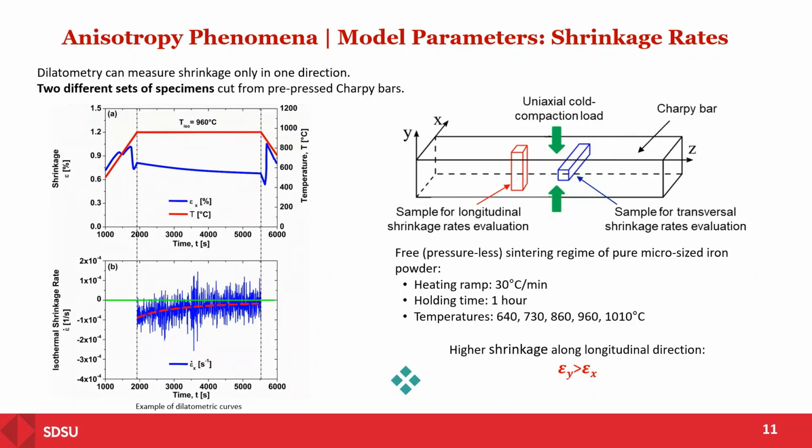So this shrinkage takes place while you still have that uniaxial pressure being applied. Right. Yeah, so in this work I also analyzed with dilatometry the same type of components, these Charpy bars, that were produced with different pressures, from, I don't know, 50 megapascals, 60, 70, 100. And with the increase of the pressure, the shrinkage that I achieved was even larger as a function of the pressure.